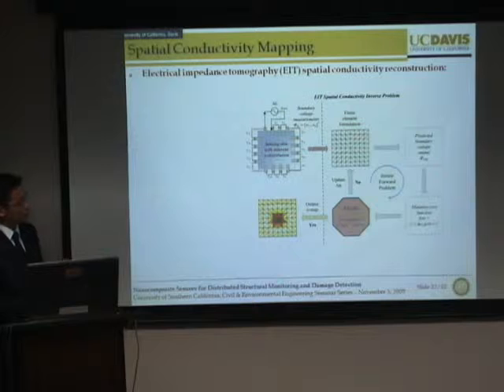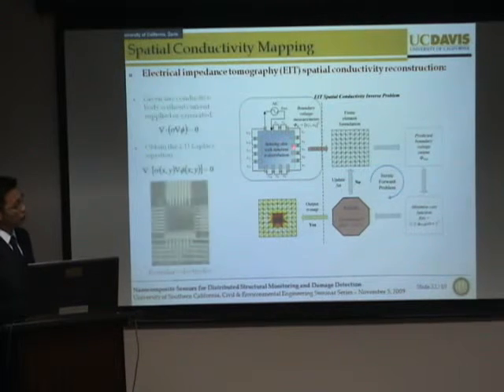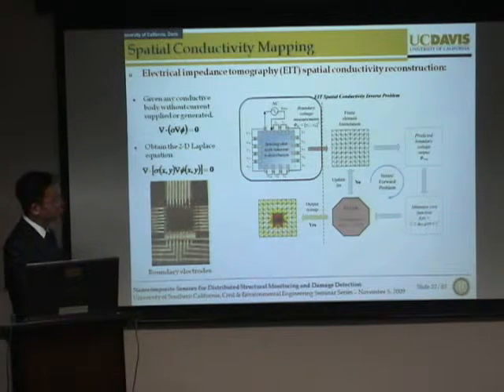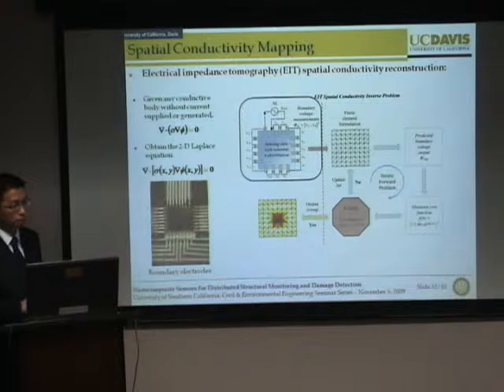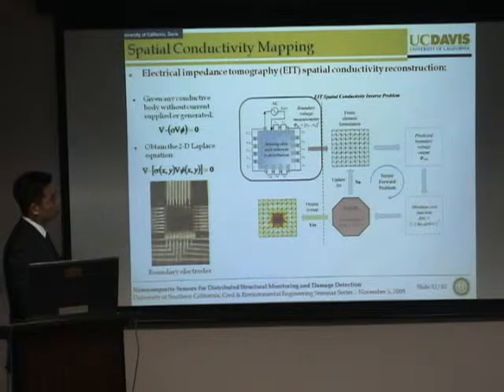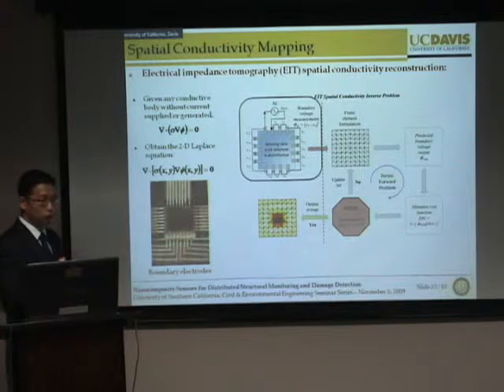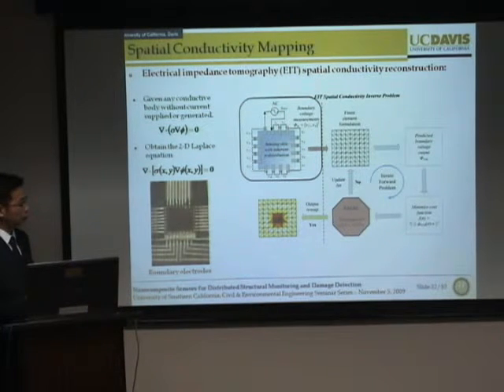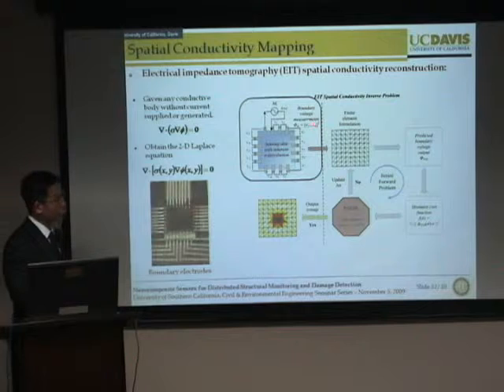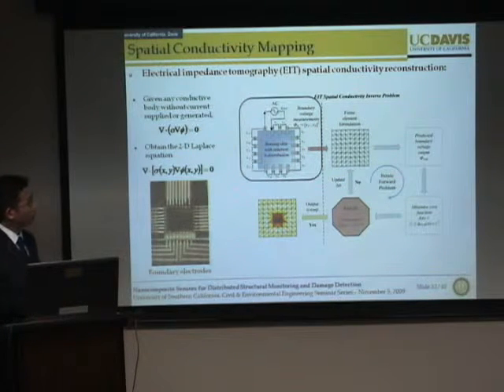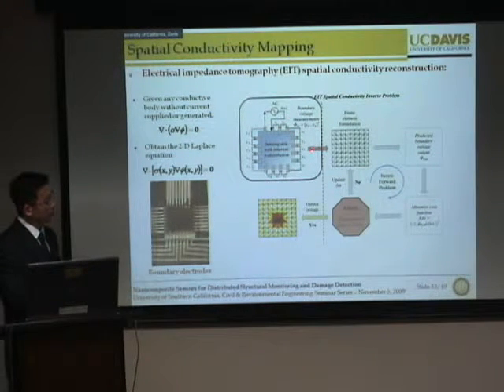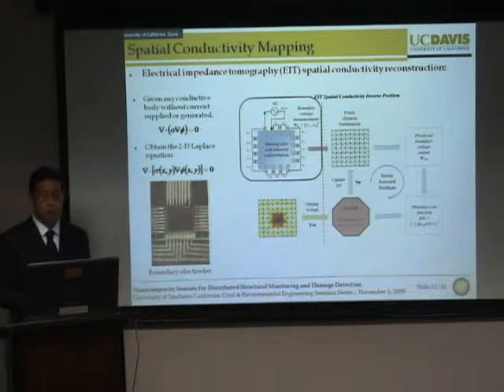So just to give you an overview of how EIT, this electrical impedance tomography, works, we can first look at just any conductive material instrumented with a set of boundary electrodes. Now, if we inject direct current or alternating current at a set of boundary electrodes, and we know the conductivity distribution of the material, we can utilize the Laplace equation to determine and predict what the boundary voltage measurements will be, or what the boundary potential drop will be, assuming that we know the conductivity distribution of the material.